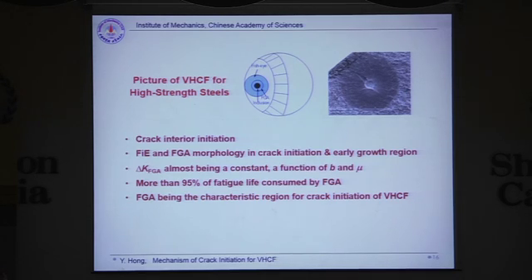It is very, very slow. So I just summarize the previous slides for very high cycle fatigue of high-strength steel. First, the crack is initiated from the interior of the material. Second, the morphology is fisheye and FGA patterns. Also, the value of delta K is stable and is a function of the Burgers vector and shear modulus of the material. Also, a large part of the fatigue life is consumed by the crack initiation process. And finally, FGA, the crack initiation region, is the characteristic region for crack initiation in very high cycle fatigue. So now we have an idea that the initiation process is so important.